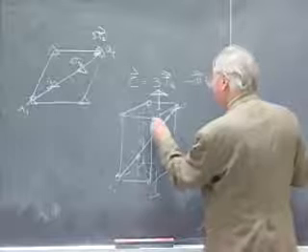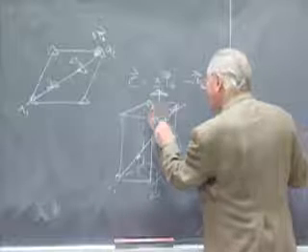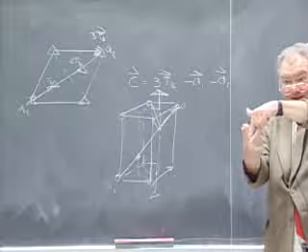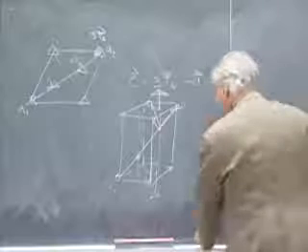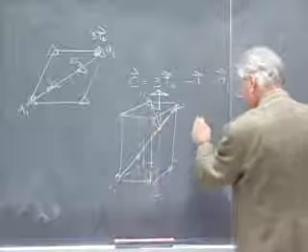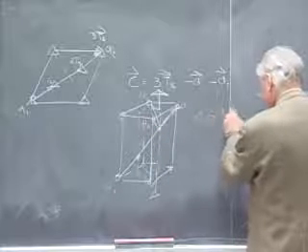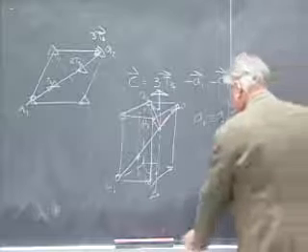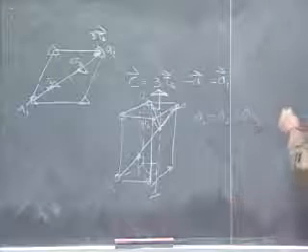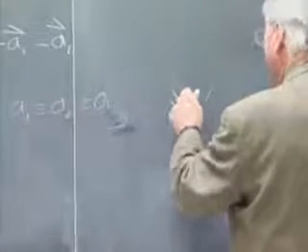If I go up to this lattice point and up to this lattice point, I have 3 translations that are straddling the threefold axis, and that threefold axis rotates one into the other. So this new definition of a cell that is in fact primitive, A1, A2, A3, they're all equivalent by symmetry. I always get in trouble when I try to draw it, but that actually defines a cell with a shape that we've not seen before. That is a cell that has the shape of a rhombohedron.